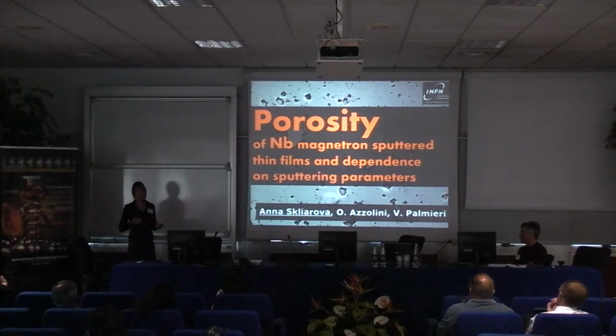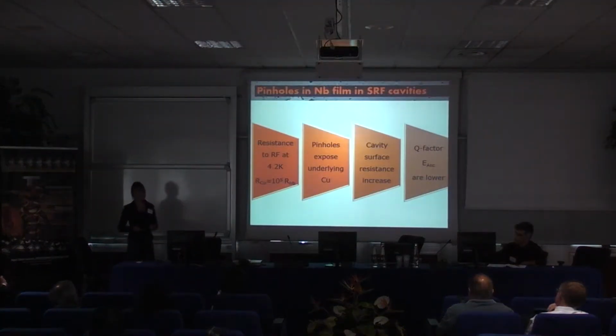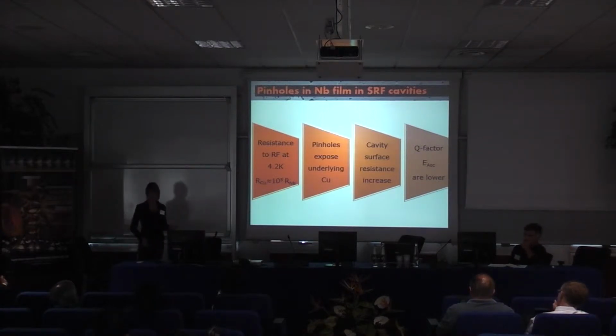Porosity can be very detrimental for niobium sputtered cavities, because pinholes in the superconducting niobium film can expose the underlying normal conducting copper material, and in this case the surface resistance of the cavity increases, and correspondingly the Q factor of the cavity and the accelerating field go lower.